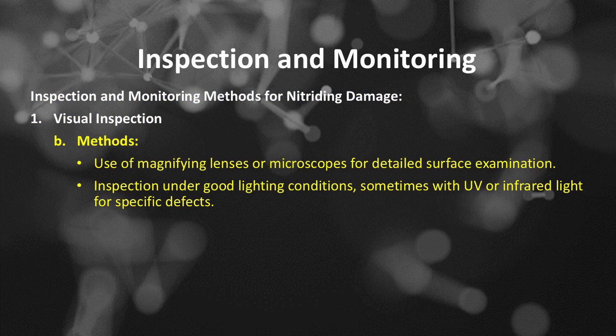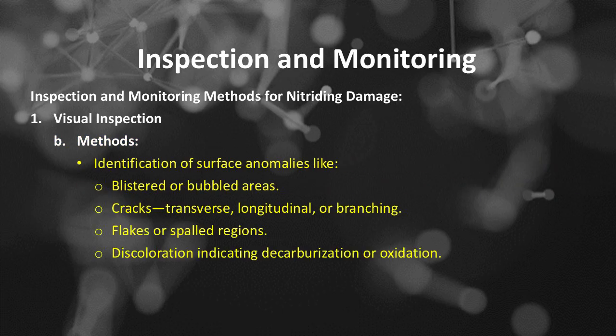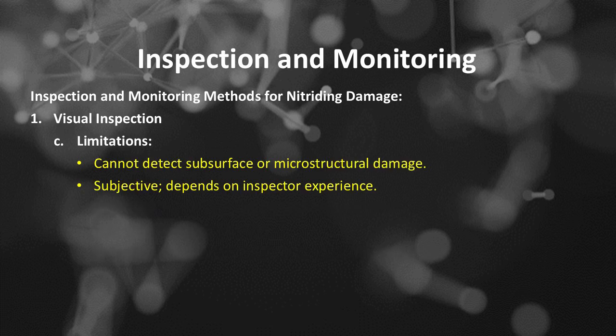Visual inspection methods: use of magnifying lenses or microscopes for detailed surface examination, and inspection under good lighting conditions, sometimes with UV or infrared light for specific defects. Visual inspection is used for identification of surface anomalies like blistered or bubbled areas, cracks (transverse, longitudinal, or branching), flaked or spalled regions, and discoloration indicating decarburization or oxidation. Visual inspection limitations: it cannot detect subsurface or microstructural damage, and it is subjective, depending on inspector experience.